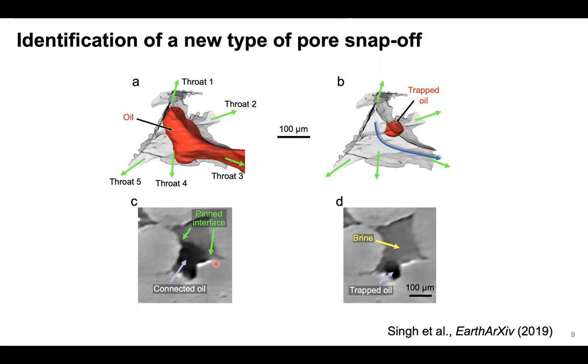So it can occur under different conditions. Let's say if we got some surface active compound, like in crude oil, it can change the wettability. But in this case, we had very simple decane, so we won't expect this sort of wettability alteration there. Second thing could be minerals. If you have different minerals, it can lead to a different contact angle. But we had 99.9% calcite surfaces in this particular rock. Just to clarify, this white thing shouldn't be considered a different mineral. It's just an imaging artifact. We start to see a phase contrast in the imaging here.